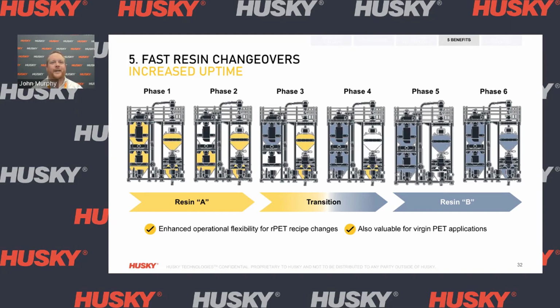And the last significant benefit that we see with the vacuum drying technology is the ability to complete fast resin changeovers in around 2 hours compared to 8 hours for a desiccant drying system. This benefit can result in an additional 6 hours of uptime, which can have a significant impact on the overall equipment effectiveness of your injection molding system. This is a very valuable piece of technology when it comes to companies that are changing materials and recipes often, giving them a higher level of operational flexibility. This is also very valuable even for converters that are running virgin applications that are changing resins quite often.